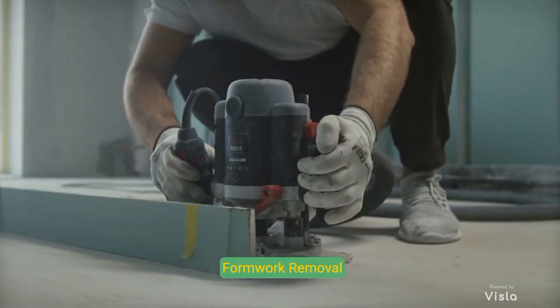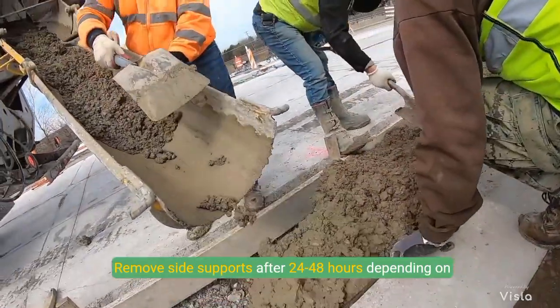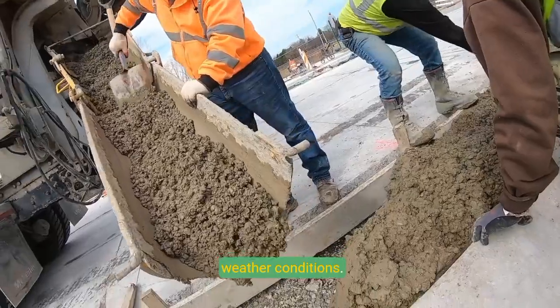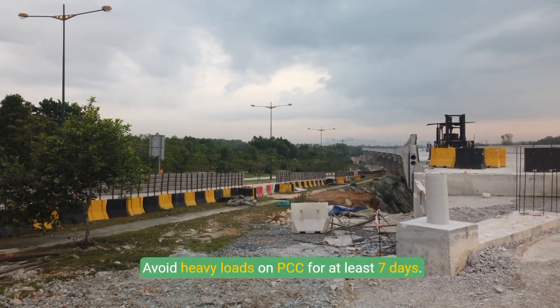G. Formwork removal. Remove side supports after 24 to 48 hours depending on weather conditions. Avoid heavy loads on PCC for at least 7 days.